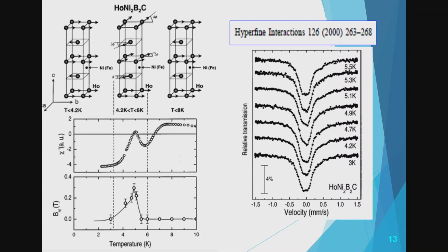And he also found the same thing in the holmium, and the holmium was a very nice system because it was superconducting, and when the system is a bit canted in a range of temperature, it introduces a pair breaking field in the system, and the system becomes normal. And after some temperature, it goes down again, it means it becomes superconductor again. So you have here a reentrant behavior where this canting of the moments generates a pair breaking field in this system. It is very nice work.